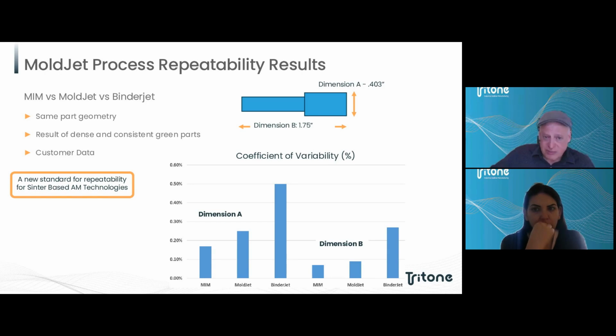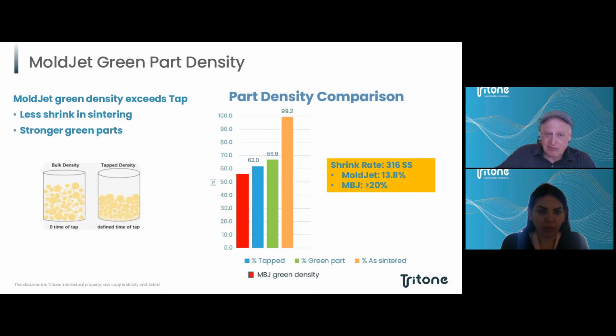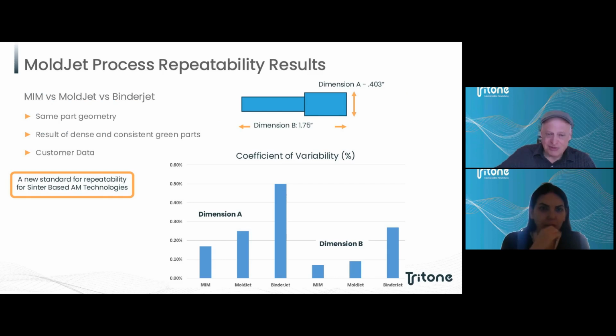MIM is the most consistent process out of the three, MIM, mold jet, and binder jet. But as you can see in both of these cases, mold jet is very close to MIM, and about more than twice, or less than half, however you want to describe the terminology, a significantly higher level of repeatability in the outcome of the parts. How does that happen? Simple. Better density in the green state. Less shrink, less variability, a more consistent output. And this is across the board.